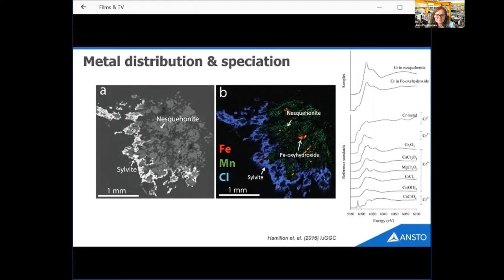This is what we know as chromium 0, 2+, 3+, 6+. And then we can compare what we see in the sample. So using the mapping capability, we can actually extract spectra from any pixel we like in the image. And so we extract a spectra from the green area where we know manganese is, in this case we're talking about chromium. So where chromium was substituting into the magnesium carbonate.